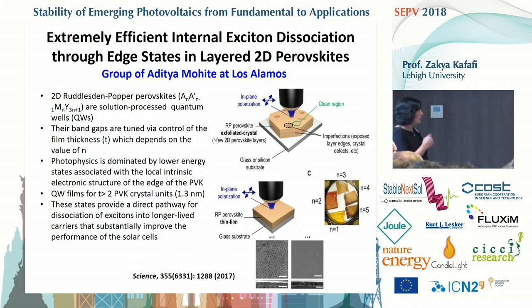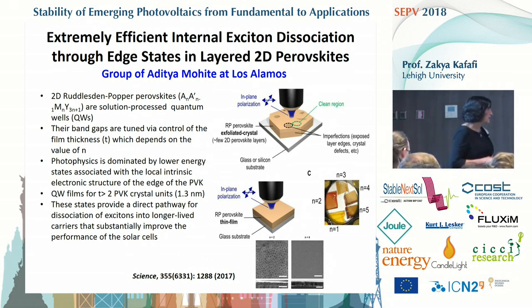Another interesting phenomenon was observed by the group of Aditya Mohite at Los Alamos, in collaboration with subgroups from Northwestern as well and Rice University. As we know, the two-dimensional Ruddlesden-Popper perovskites are solution-processed quantum wells. Their band gaps can be tuned via control of the film's thickness, which depends on the value of n. And they showed that the photophysics is dominated by lower energy states associated with the local intrinsic electronic structure of the edge of the perovskite films.